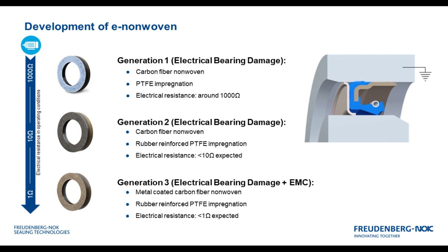So what we've done at Freudenberg is developed a technology to help meet this request from our customers, and that is what we call the electrically conductive radial shaft seal, or an e-nonwoven. So what we've done is we developed a nonwoven material that is based on carbon fiber and is electrically conductive. And you can see pictured here on the right, we have a traditional radial shaft seal with a nonwoven excluding device that actually is electrically conductive. So this nonwoven is making that electrical connection between the shaft, that dynamic shaft, and the static housing. So when that excess electric potential is built up within that unit, it allows a safe discharge of that electric potential along this path to prevent any damage to any other components within the unit.